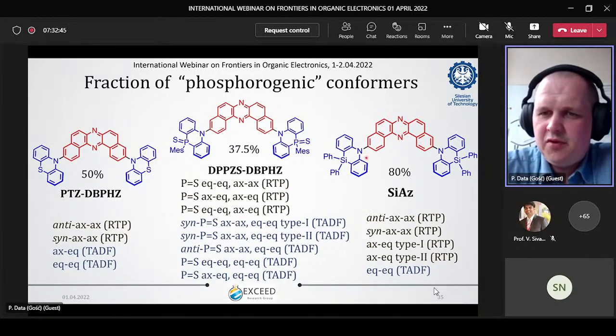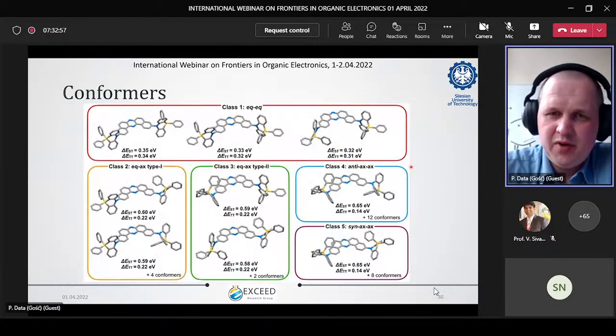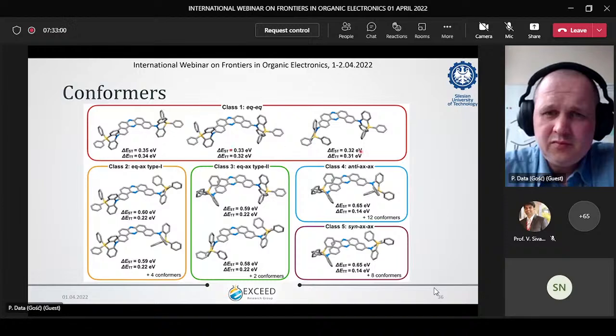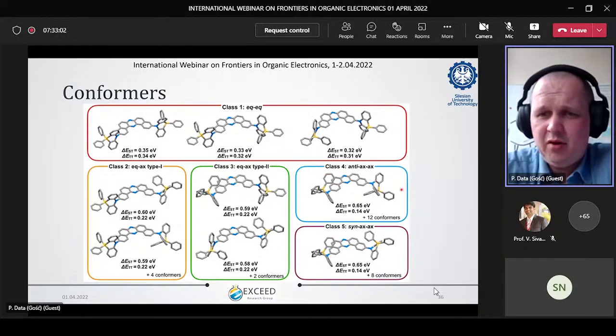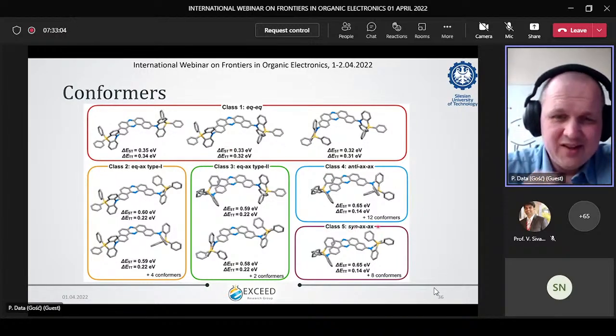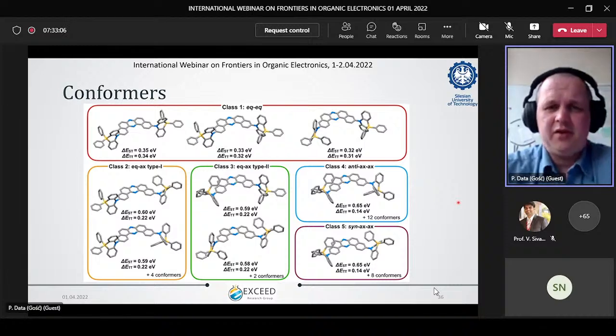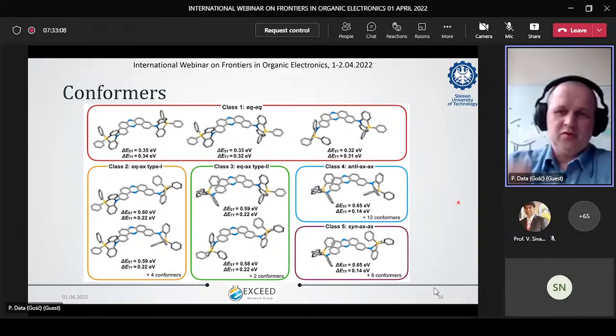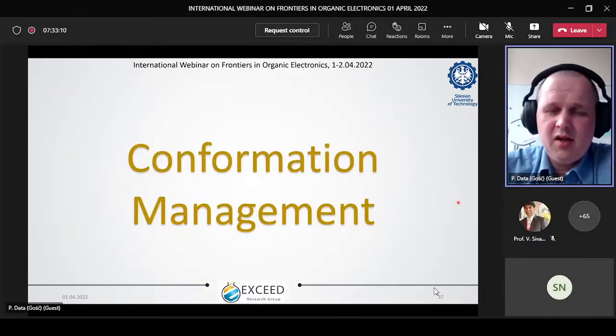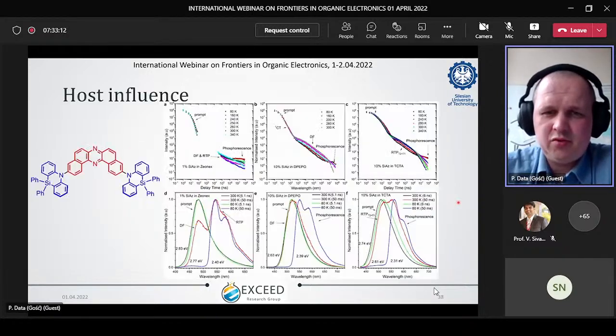And with Yohei, we designed more silicon-based derivatives, which showed really nice properties. In this case, most of the conformers were phosphorescence-based conformers. Through the analysis, the number of conformers was more than 35, as I remember, but we divided them into 5 groups. So how do we manage those conformers?